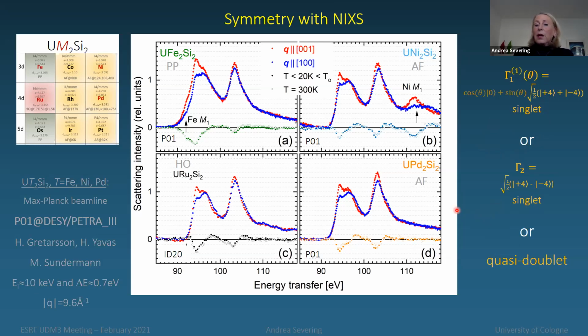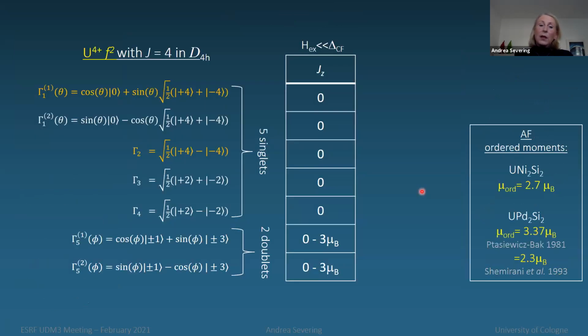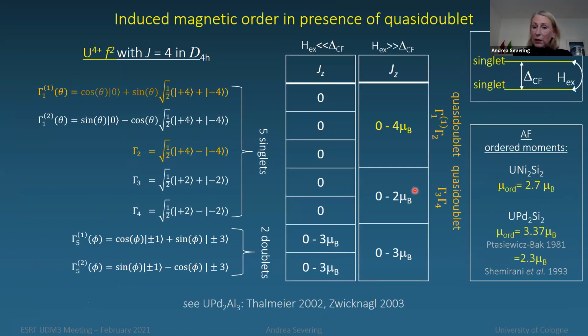You may wonder, I'm telling you we have singlet ground states, but we have antiferromagnets. How can that be? Because indeed, a singlet state does not carry any moment. Only the doublet states do, but the nickel to silicon 2 and also the palladium to silicon 2 have really large ordered magnetic moments. Well, that can be if you accept that we have to deal with induced magnetic order in the presence of a quasi-doublet. If you have two singlet states, relatively close in energy, closer in energy than an exchange interaction would be, then we could have any ordered magnetic moment between 0 and 4 Bohr magneton. And that would accommodate actually these large moments.